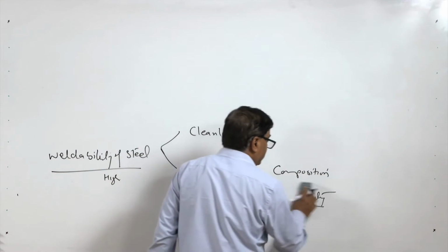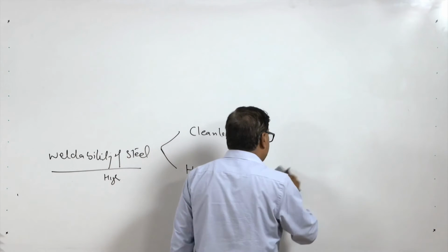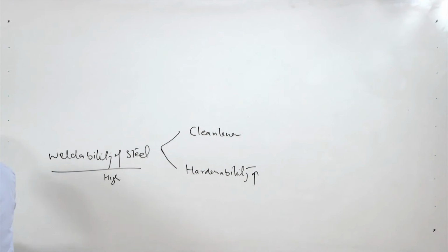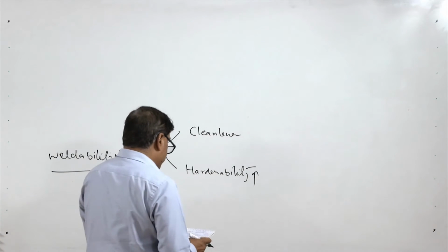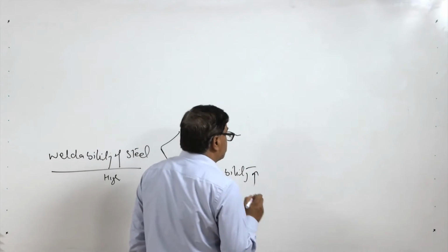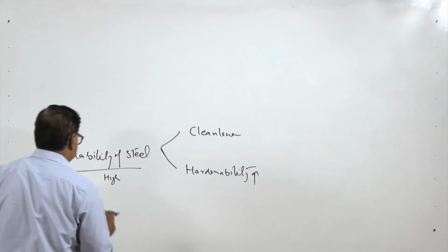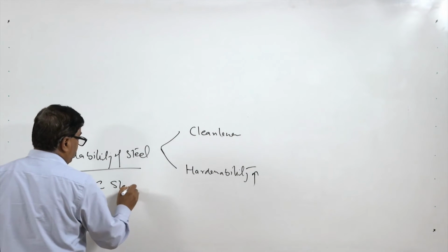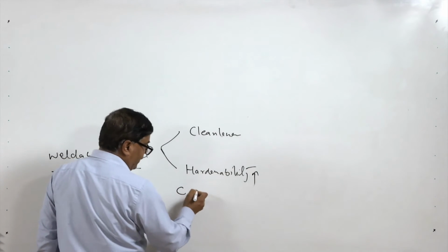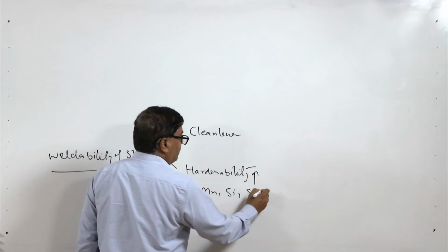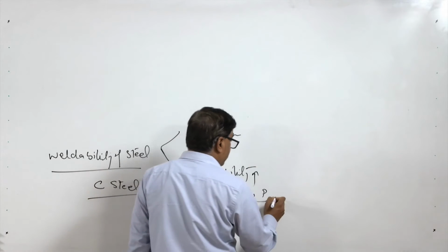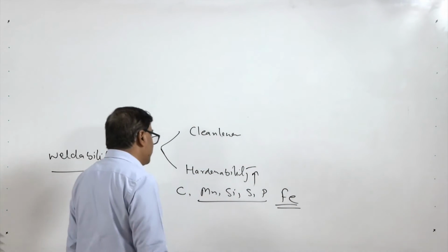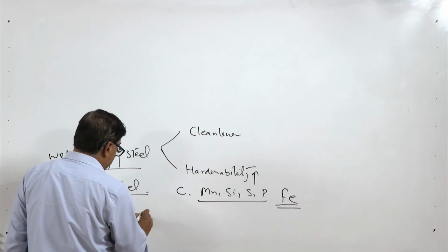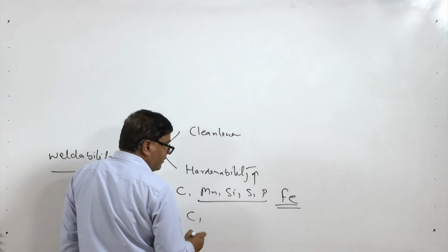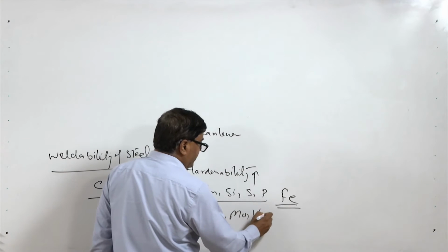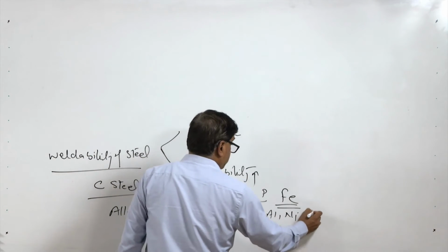So, one of the main factors that affect the hardenability of the steel is the composition. What are the factors related to the composition of normal steel? As I have said, a typical carbon steel will primarily have carbon, manganese, silicon, sulfur and phosphorus, where all these are residual elements. Apart from this, the main element, the matrix, is iron, while in the case of alloy steels, apart from carbon, other alloying elements are also controlled, like chromium, molybdenum, vanadium, aluminum, nickel, tungsten, etc.